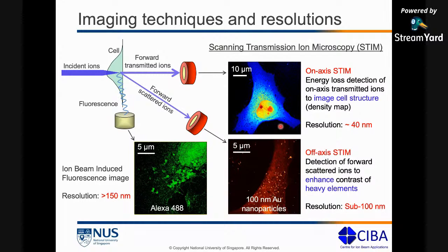Right. So compared to that, if you look at the off-axis STIM image, because it's an image taken from the forward scattered ions, the resolution is not as good as the on-axis STIM image. It's about 100 nanometers, sub 100 nanometers. But here we have a very distinct advantage that we don't get in an on-axis STIM, and that is we can get elemental contrast from an off-axis STIM image, because these are forward scattered ions. So now, based on the energy of these forward scattered ions, we can identify the different elements that could be present in your sample. We cannot get this in an on-axis STIM image, right?